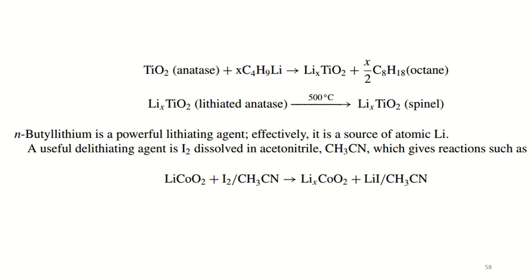LiCoO2 plus I2 in acetonitrile changes into Li(x)CoO2 plus lithium iodide in CH3CN. Products with a large range of x values are obtained by controlling the amount of iodine used. The driving force is the formation of lithium iodide, which is soluble in CH3CN.